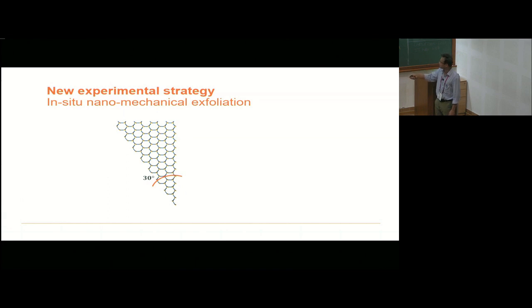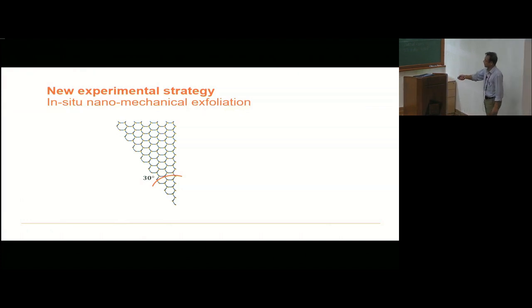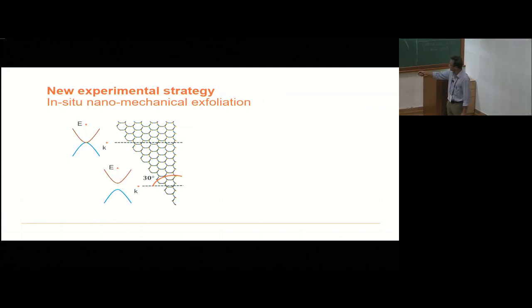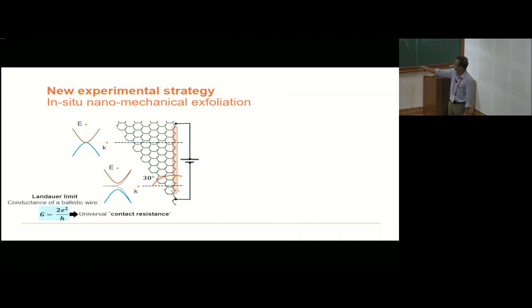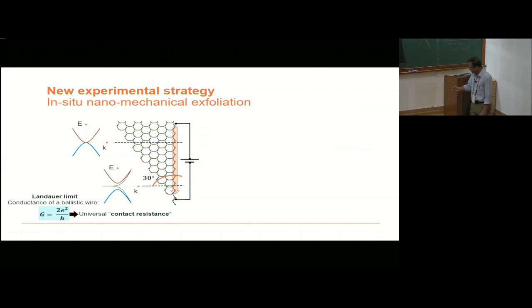side. This is gapped because armchair edges don't have zero energy states, whereas edge states on the zigzag one has. So in this region where the quantum confinement is very strong, there is a gap over here, this is the quantum confinement gap. However, the edges will conduct in this direction, and if you apply a battery between the two, then you should get electrical conductance of 2e squared by h. That was the idea behind our experiment that we tried to do.